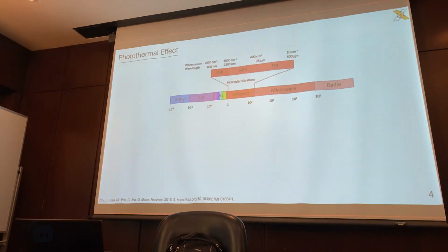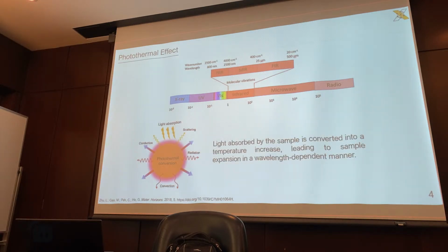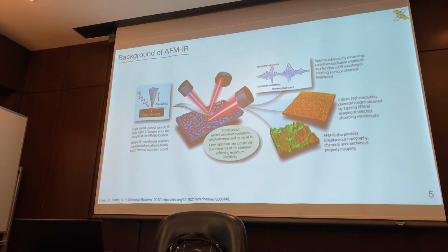So here is the visible region. My laser is a little weak today. So people saw the photothermal effect as a way of bypassing this limitation or the diffraction limits of light, because if our target is looking at molecules, then why not take advantage of certain wavelengths of light that excite these molecules? And so people began looking at the photothermal conversion, because if we look in the infrared region, this is the region that begins to create molecular vibrations, and to where we can actually get a response from our materials if we shine them with the correct wavelength. So this is the photothermal effect, and this is how we're going to bypass the diffraction limit of light.